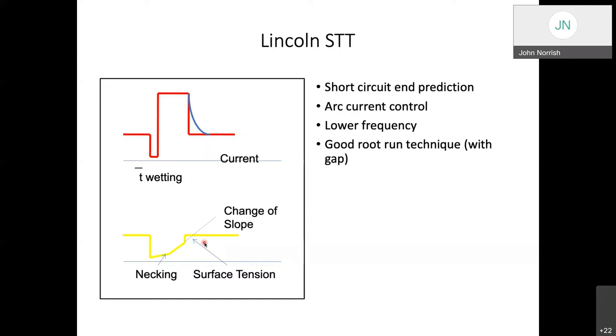And then Lincoln Electric in the States developed a technique for detecting the end of the short circuit by using the change in the rate of slope of the voltage during the short circuit, and that was much more reliable in predicting the end of the short circuit, and they could then turn off the current very reliably. And this became known as STT. It was probably one of the first waveform controlled short circuit processes, and was used very much across the board for lower current operations, thinner materials, but it also gave very good root penetration control.